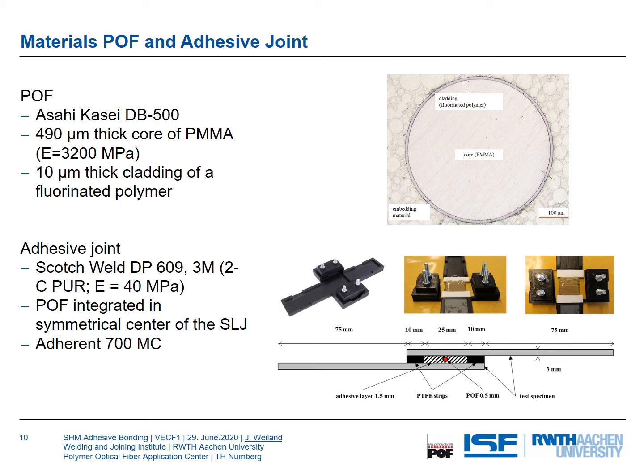For example, the elastic modulus of the fiber from PMMA is around 3000 megapascal, and the elastic modulus of this adhesive is about 40 megapascal. If we compare this to the elastic modulus of a glass fiber, for example, which is 80 or 90,000 megapascal, then with that adhesive we are able to really change the cross-sectional shape of these POF. If we use another adhesive which is stiffer, like an epoxy, we come into the same range of elastic modulus of these two materials. So this method is really an adhesive-dependent method and not an adherent-dependent method.